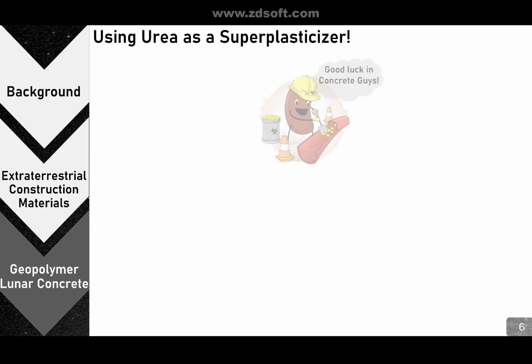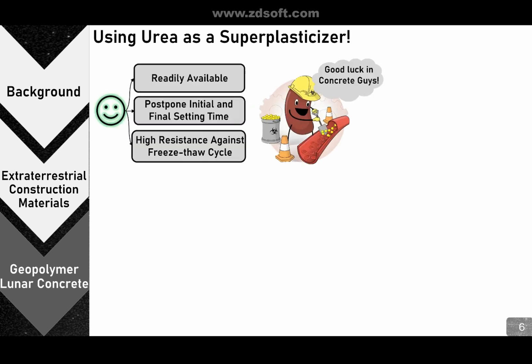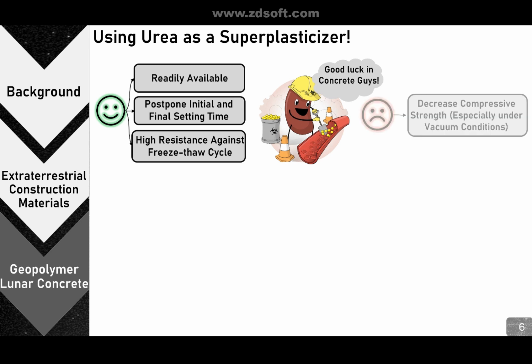First off, it can be easily obtained whenever humans are present, even on the Moon. Additionally, longer setting times after using urea can help us maintain a continuous flow during the 3D printing process. And it was observed that using urea results in a high resistance against freeze-thaw cycles. However, the compressive strengths of samples made with this material will drop up to 50% under vacuum conditions.